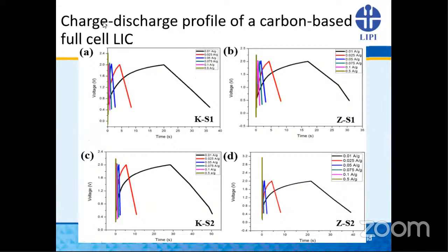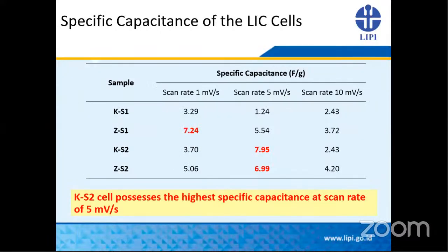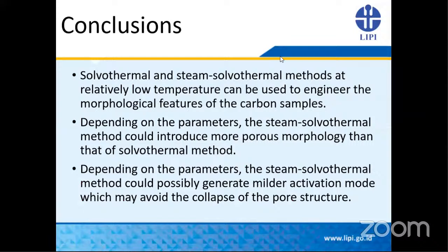And this data also demonstrates the charge-discharge profile of the carbon-based full cell LIC. So we can see here for the sample KS2, the charging profile is longer than the other samples, and it represents the best result compared with the other samples. So we also calculated the specific capacitance. We found that the KS2 cell possesses the highest specific capacitance at a scan rate of 5 millivolt per second. So for the conclusion, this is some of our results.